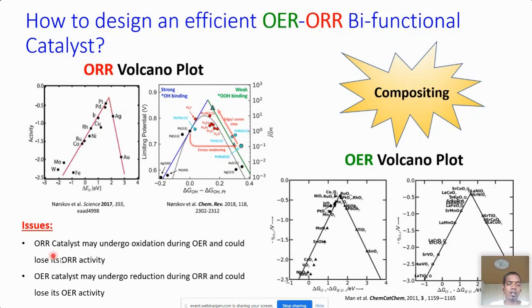But the issue is that ORR catalysts, which perform the reductive potential reaction, usually perform well when their surface characteristics are retained. But when we have a composited catalyst with part ORR catalyst and part OER catalyst, when you perform OER, these materials can be oxidized to oxides and hydroxides, which may not be as active as the metals in ORR when you perform discharging again. This means these composites could actually be destroyed during the charging and discharging cycle because of instability in the counter reaction. So this is the main issue with compositing. But what can we do about it?